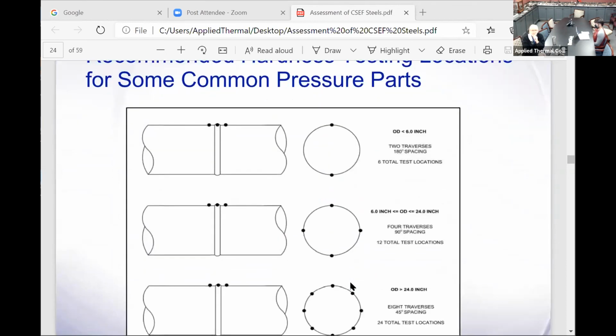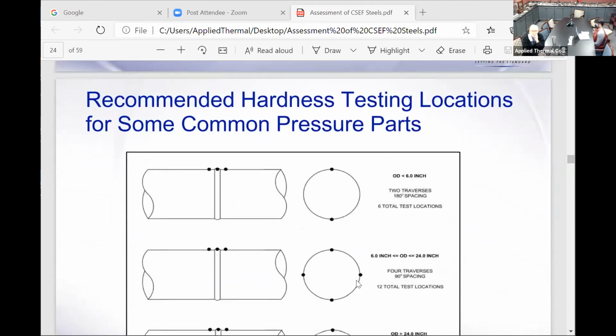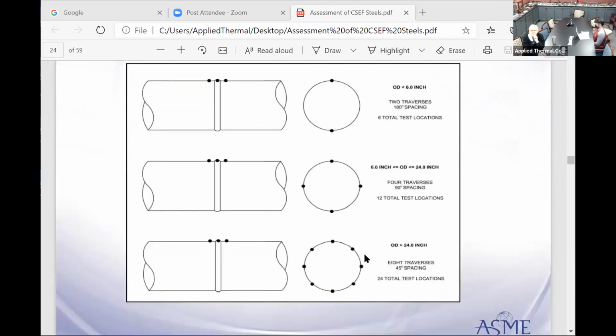Quickly, some common places to remember when you're doing hardness testing: you want to get multiple locations. Obviously, you want to get the base material, the substrate, the weld itself, and you want to get plenty of representative samples. Depending on the OD of the pipe or tube, this tells you how many points you want to get along the circumference of the pipe.